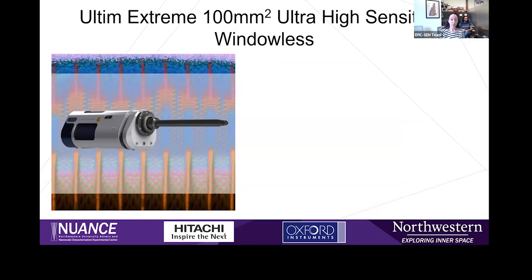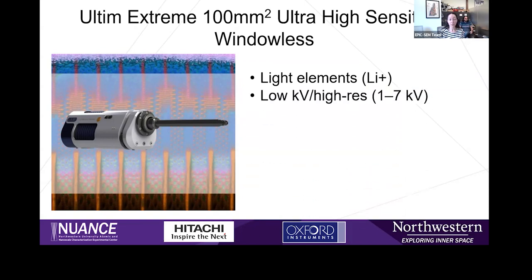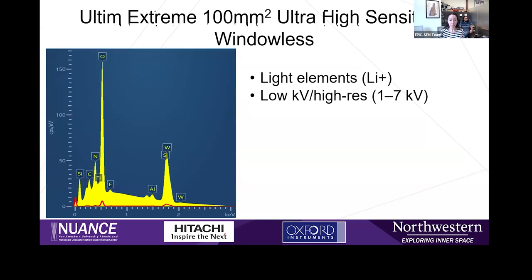So next, we're going to have an Ultim Extreme detector from Oxford Instruments. This detector is going to be your go-to detector if you're interested in the light elements and rated down to even lithium. It's also going to be your go-to detector for very low kV EDS, as low as around 1 kV, and you can use this detector up to about 7 kV.